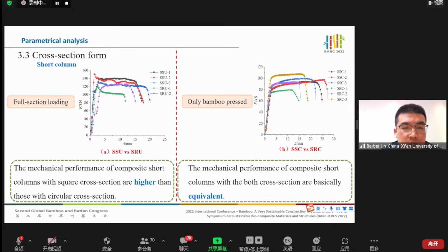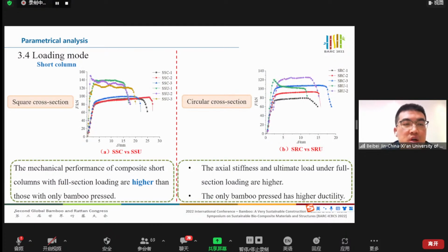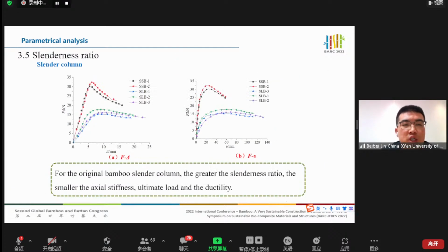Cross-section form for the short column, full section loading mode: the mechanical performance of composite short columns with a square cross-section is better than those with a circular cross-section. With only the bamboo compressed, the mechanical performance of composite short columns with both cross-sections is basically equivalent. Loading mode for the short column with a square cross-section: the mechanical performance with full section loading is higher than with only the bamboo pressed, because the mortar and the bamboo both withstand the load. With the circular cross-section, the axial stiffness and ultimate load on the full section loading are higher, and when only the bamboo part is pressed, it has a higher ductility.